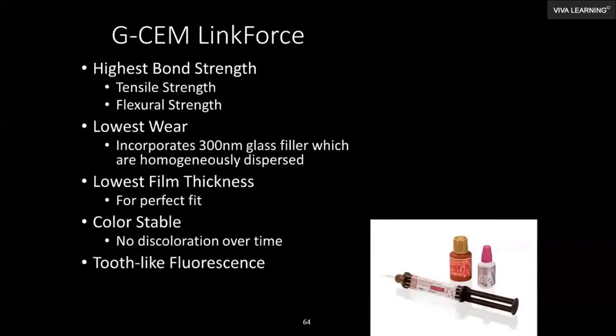The thick ones, you start pressing really, really hard, and what ends up happening is you expel a lot of the cement out of that veneer and have just a thin film thickness. Or in this case, if you have a 3 or 4/10 of a millimeter thick Emax or lithium disilicate type veneer, or a Lisi veneer as we have in this case, you don't want to break that veneer. So if something's really thick and you have a 2/10 of a millimeter veneer, you could break it.